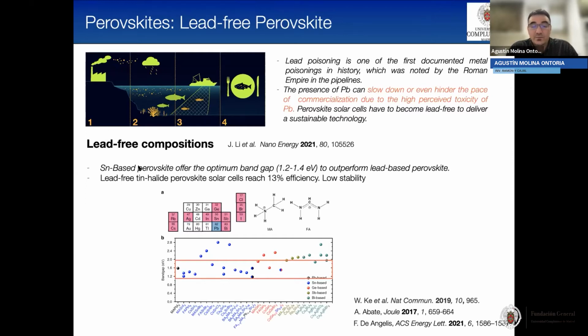The basic one, the most used one, is the tin-based perovskite that offers an optimum band gap of 1.2 to 1.4 electron volts that theoretically can outperform lead-based perovskite. The only problem with this is that they are not reaching or matching the efficiency of lead-based perovskite, and they are showing even lower stability than lead-based perovskites. Here I show you a graph of different materials that have a band gap between 1.1 and 2 electron volts, and that can be potential candidates for photovoltaic applications.